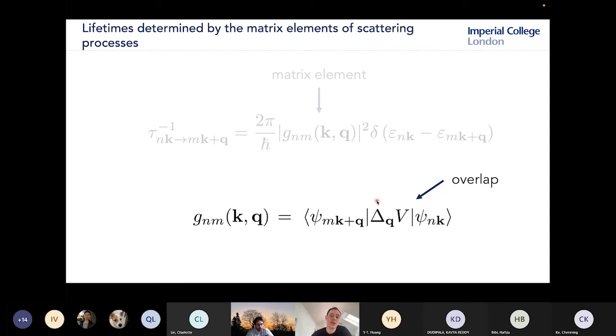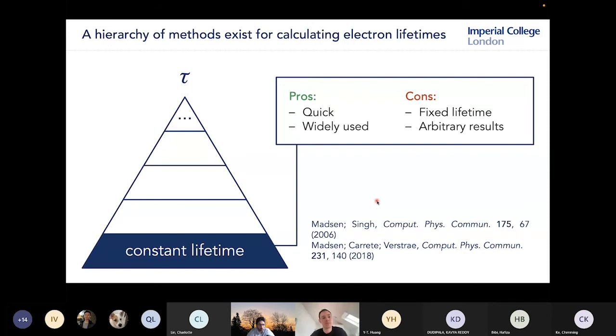And part of that is that there are many different scattering potentials that we have to consider. So you can have scattering of electrons due to vibrations in the crystal, due to impurities, grain boundaries, and things like that. Now, over the last 50 years, there's been a hierarchy of methods developed for calculating these electron lifetimes. The most commonly used and the most basic is what's called the constant lifetime approximation, where basically you don't bother calculating anything, you just set the lifetime to a value. Maybe it's the average of some materials that you measure experimentally.